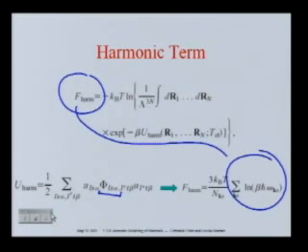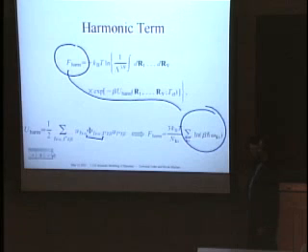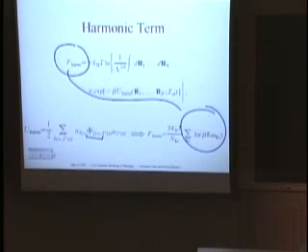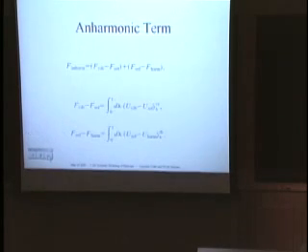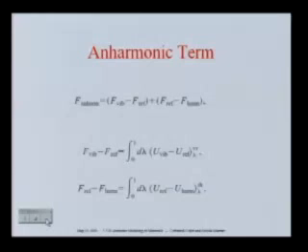This can give me the change in the vibrational free energy in going from one phase to the other, and I just calculate the phonon frequencies in two different phases. What is more intriguing is the calculation of all the nonlinear terms that can be very important at high temperature.